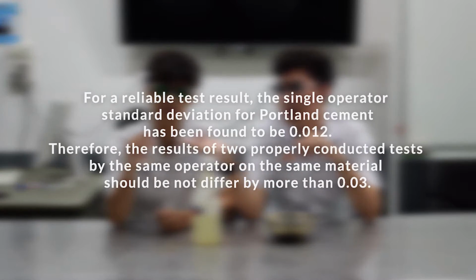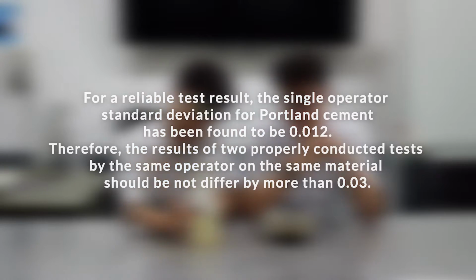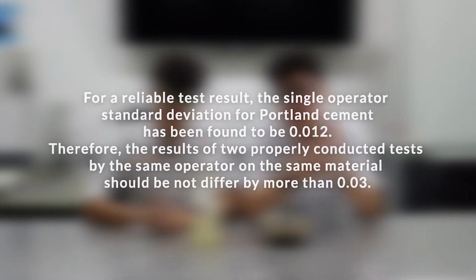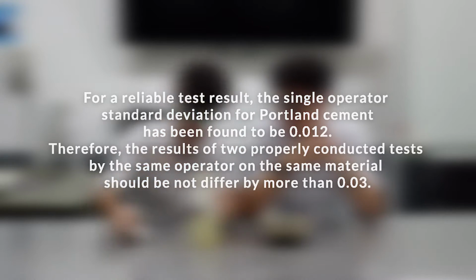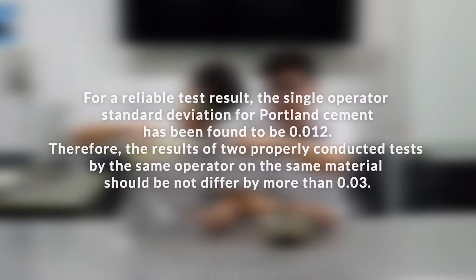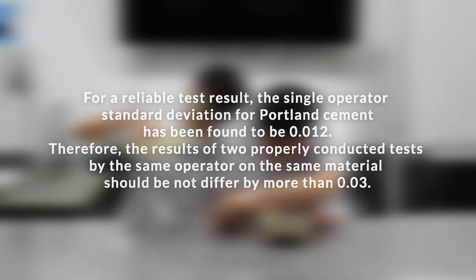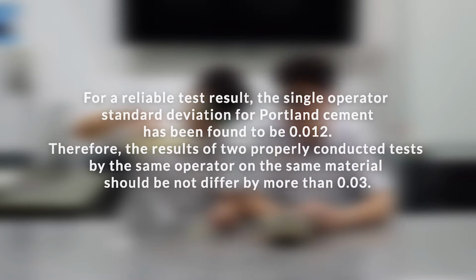For a reliable test result, a single operator standard deviation for Portland cement has been found to be 0.012. Therefore, the results of two properly conducted tests by the same operator on the same material should not differ by more than 0.03. And the multi-laboratory standard deviation for Portland cement has been found to be 0.037. Therefore, the results should not differ by more than 0.10.